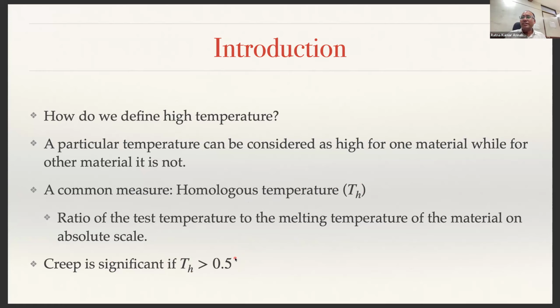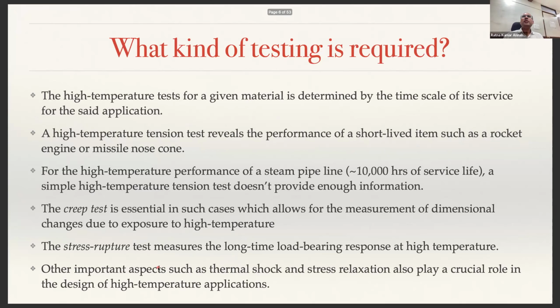So now we know the melting temperature of each material is different, and hence it is logical to define this measure with respect to the melting temperature. So that is basically the ratio of the working temperature to the melting temperature, called homologous temperature. So if your homologous temperature is greater than 0.5, that means if your operating temperature is greater than 50% of the melting temperature of the material, that is when creep is significant. That is how high temperature is defined. Okay.